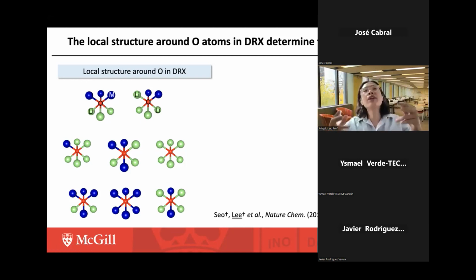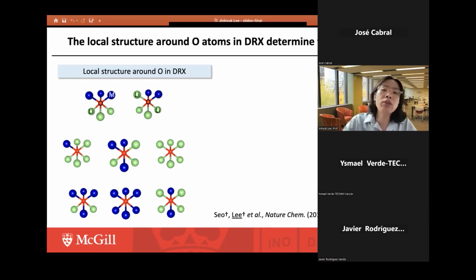And now, when we think about electrons getting oxidized, that requires the electrons to be at a decent energy level, so it is possible to extract electrons from that particular level. If the electron is too stable, then that electron will not be extractable upon charging. And we know that the electronic structure around oxygen or other transition metal cations will be largely determined by the local structure around them. So we can imagine that all these different oxygen atoms may react differently upon an oxygen redox process, right?